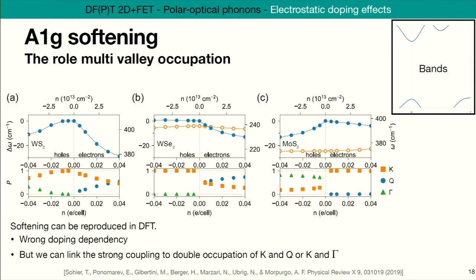Now, why is there softening on the other mode, and why is it only for electrons and not for holes? What's happening there? We can do some DFT calculations. We are capable of doping the system with our gates, and we're capable of computing the phonons. So we can do this in those same three TMDs as the experiment, and this is what we get here in blue. In blue, this is the mode that we are interested in. And we get some softening, but not quite the right doping dependency. So here, for this material, it indeed softened for electrons and not for holes. This is what we saw in the experiment.